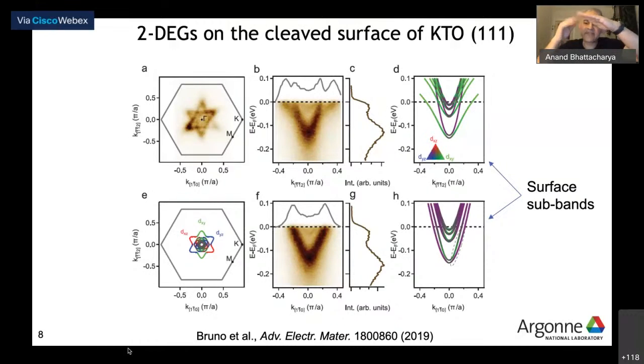You have a 2-deg, so there's some sort of confining potential near the surface, and that causes multiple bands, multiple levels, to show up, and indeed they see that. So they see different copies of the band structure in their 2-deg, depending on the carrier density.